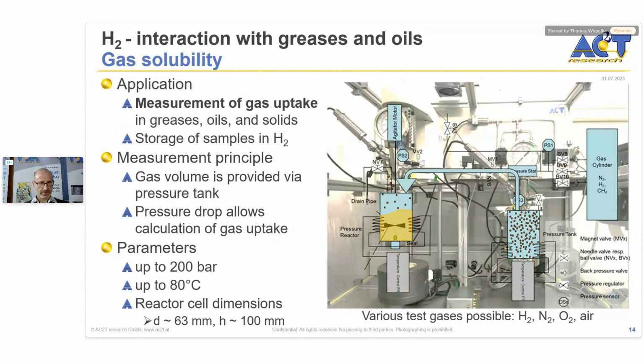The next method is interesting to investigate the hydrogen uptake or gas uptake into greases and oils. So the working principle is that you fill the pressure tank on the right side with the gas you are interested in. It can be filled up to 200 bars of gas pressure. And in the left cell, in the pressure reactor, you fill the lubricant you want to investigate. And once this is done, you open a valve between these two tanks. And these two tanks are more or less then under the same gas pressure. And over time, you will realize a pressure drop in the tank system, and this pressure drop gives you information about the gas uptake into the lubricant.